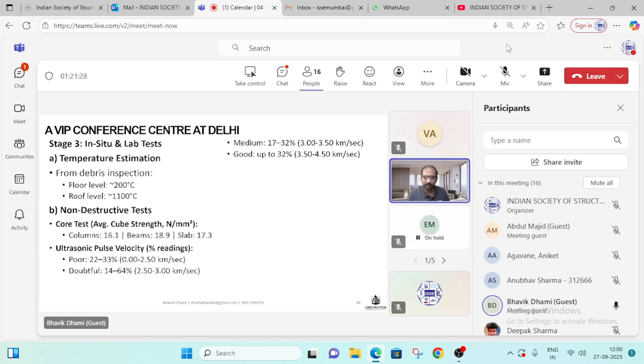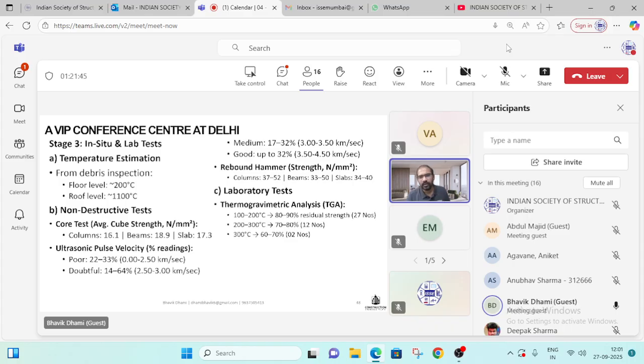And based on the assessment of the UPV, they were able to identify, on the velocity, what percentage of the readings fall where. If you see, it is a mix of poor, doubtful, and medium. So it is a whole. You cannot depend on one. Same goes with your rebound hammer. Now, this part, laboratory test, it might be on a little higher side, like when it was exposed to certain temperature.